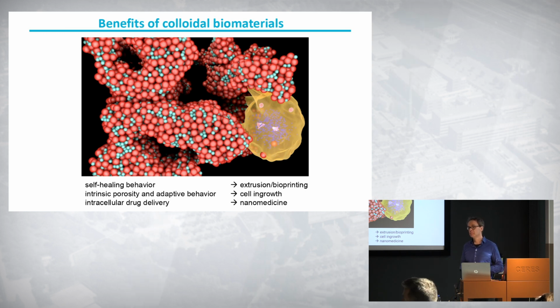It can still be degraded by the cells then? Yeah. I know from gelatin and most of the crosslinked ones that cells can't really degrade it anymore. Oh yeah, but it can be degraded. There are proteases present, like for collagen, so the degradation happens. Actually, it's a challenge to reduce the degradation. So now it's within a few weeks to one or two months, then it's degraded. As a composite material, that process is reduced, so that's a tool to reduce degradation speed.